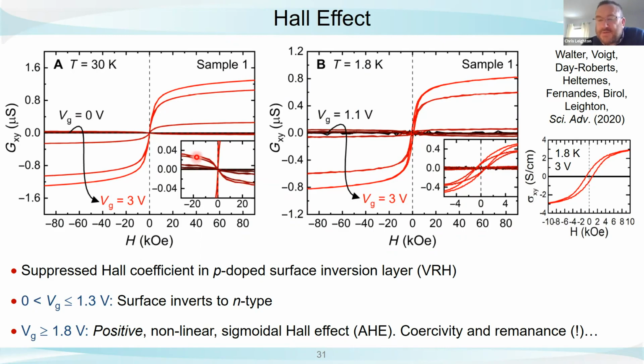So it looks like you're putting electrons on the surface of the material, and then very abruptly, at about 1.8 volts, out pops this huge positive Hall coefficient. And that huge positive Hall coefficient, it's nonlinear, it's sigmoidal in shape, it saturates with field. If you go down to the lowest temperatures we measured, which is 1.8 Kelvin, and look at that in a bit more detail, it turns out, in fact, the loop really does open. So you end up with finite coercivity and finite remnants.